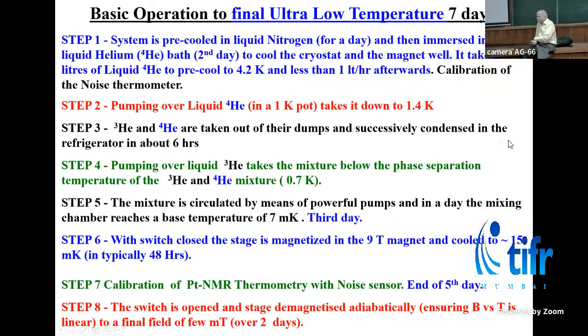I must say that it takes time, because we had to calibrate the sensors at millikelvin. It works up to 10 millikelvin with the standard calibration, but every time you do the run, that platinum NMR has to be calibrated with respect to sensors at high temperature.